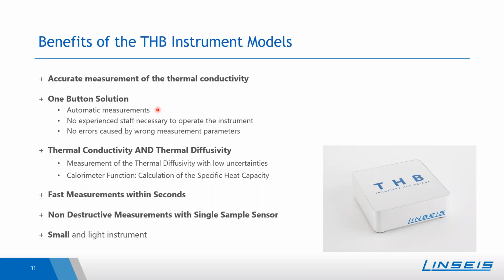Additionally, it's often not easy to determine which property or which settings are the best to be able to measure the material. The THB can do this automatically so that the errors caused by wrong measurement parameters will be lowered or will just not be there. The measurements can be performed very fast. So you have seen within the short video how long a measurement of a polymer, for example, takes. It's just about 30 seconds. Metals, for example, can be measured within about 10 seconds. The maximum measurement time is typically within a few minutes, up to 3 or 4 minutes.